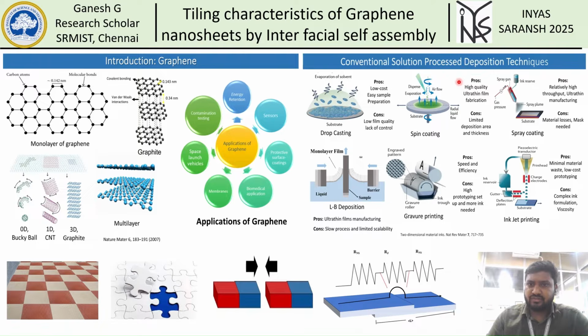So we have conventional solution-process deposition techniques like drop casting, spin coating, spray coating, LB deposition, gravure printing, inkjet printing, and so on. But they have advantages as well as a few disadvantages. Like inkjet printing, you need to control the viscosity, and for gravure printing, wastage of material. LB deposition takes a lot of time, and with spin coating, we can't coat large areas. And with spray coating, there is the mask and the alignment.